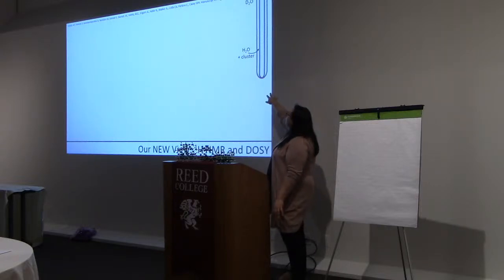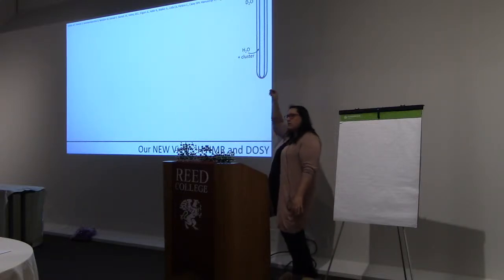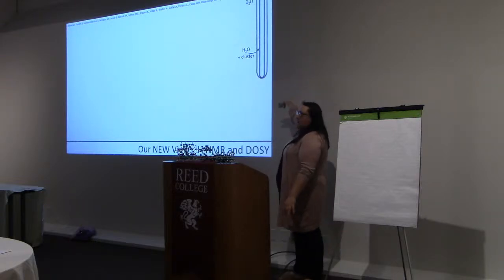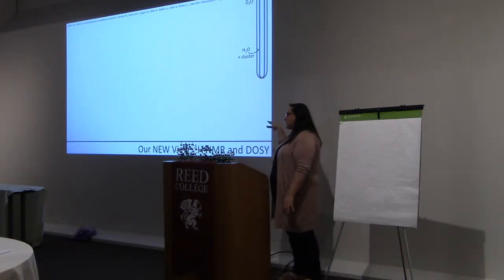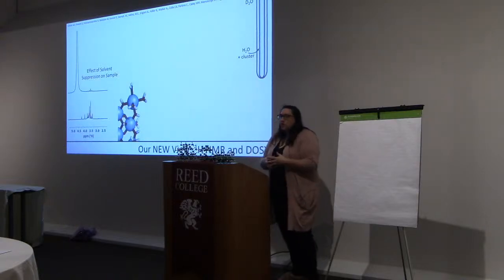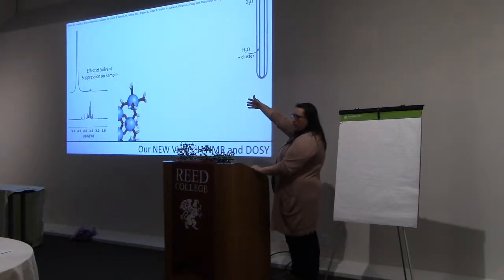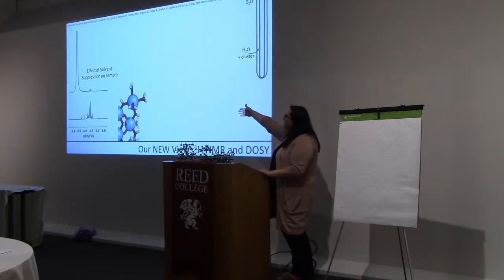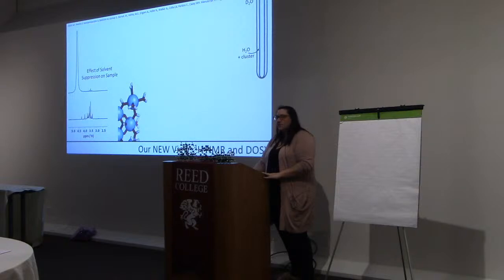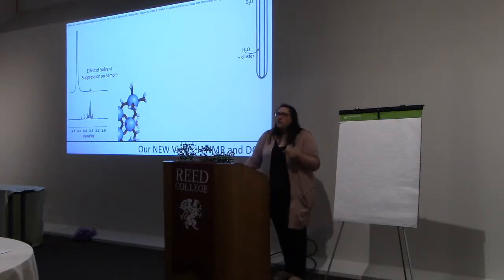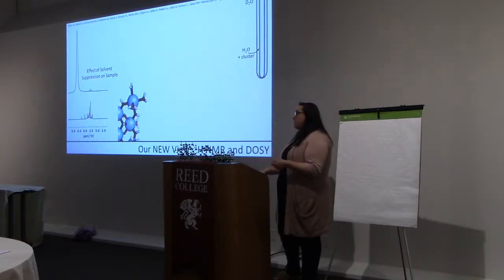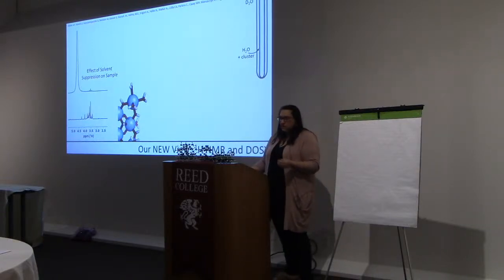And so we got NMR tubes with coaxial inserts that we could put our D2O to lock inside, and then our clusters would not be interacting with the D2O. Then we did solvent suppression because we had a huge water signal because of that choice. And so you can see before our solvent suppression, it is very hard to make out any of these signals, but afterwards they become pretty prominent, and all of those signals are corresponding to hydrogens on hydroxide bridges in our clusters.